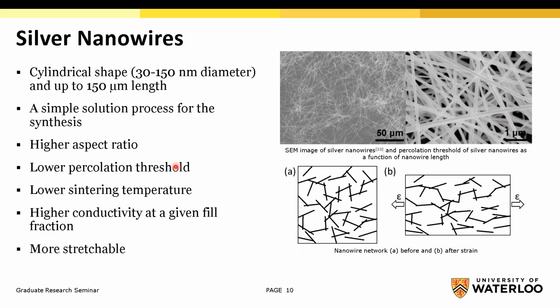In comparison to nanoparticle and flake inks, where you usually need at least 70% silver to have a conductive network, with silver nanowires 1% silver nanowire might be enough to have a conductive network. Since they have a really high aspect ratio, you can have a much lower percolation threshold. They have a much lower sintering temperature and higher conductivity at a given fill fraction. One of the main advantages of silver nanowire inks is, as you can see here, that they can tolerate really high strain. This is really advantageous for stretchable electronics.